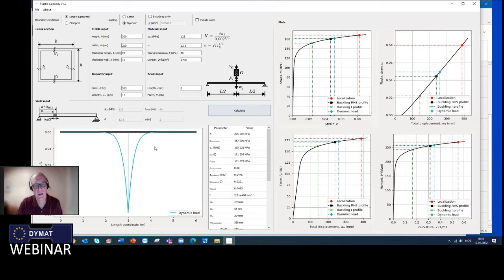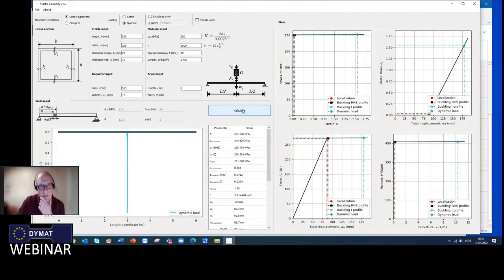Then you see that the spread of the plastic deformation is increased along the beam. Now the strains are much lower. Here's the localization strain, but here you see that I have a challenge with buckling. But if you now, for instance, have a material where the hardening is almost zero, let's take 250, and then you take an n which is 1000. Then you see everything localized in the center.